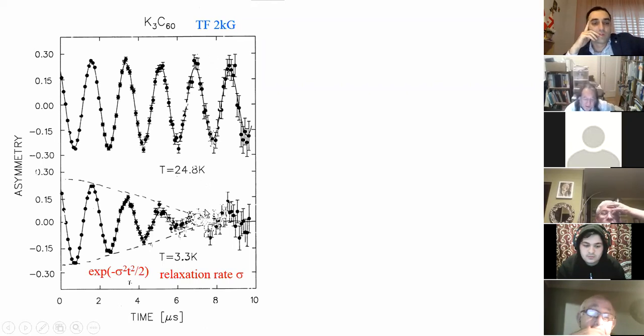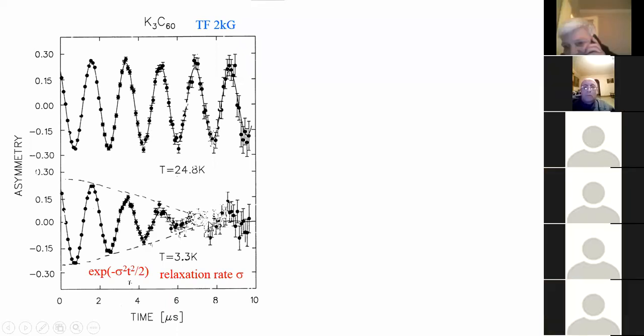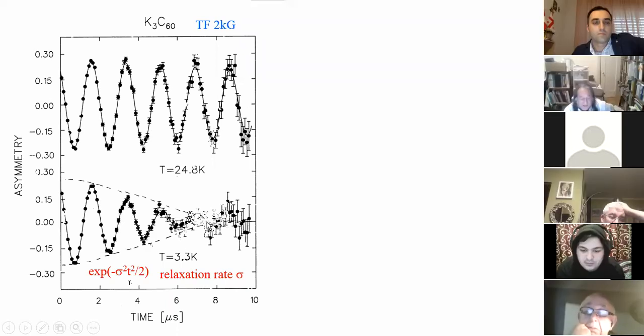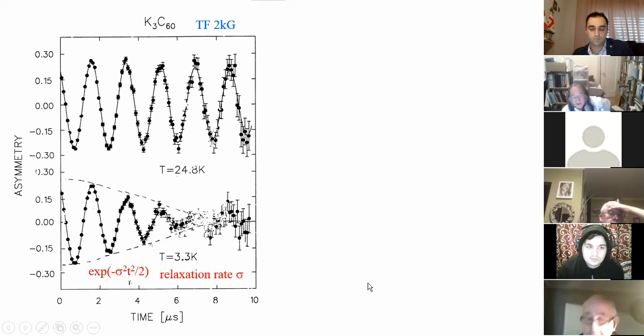2 kilogauss. But if you cool down this system into the superconducting state, what you will see is that this oscillation shows damping. This damping is very much related to the fundamental length scale of superconductivity and allows us to do some physics. This damping can usually be fit with a Gaussian function. And we show you many of the data of what we call the relaxation rate sigma, which is this Gaussian damping rate. Essentially, please remember that every time I show this relaxation rate, it is just the rate of this damping. So why do we see this damping in the superconducting state?